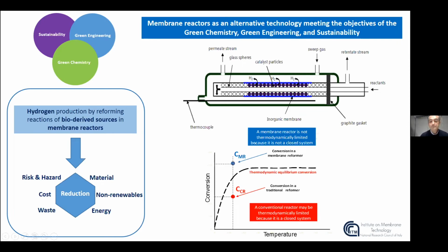And in particular, due to the presence of the membrane inside the membrane reactor module, it's possible to show this theoretical graph, in which, at the same temperature, for a membrane reactor operated at the same conditions of an equivalent conventional reactor, the conversion can overcome the thermodynamic equilibrium conversion of the equivalent traditional reactor. And this is because a membrane reactor is not a closed system, and therefore it is not limited by the thermodynamic equilibrium conversion. Otherwise, by reaching the same conversion of an equivalent conventional reactor, a membrane reactor can be operated at milder conditions, lower temperature, lower reaction pressure. And this allows to reduce the energy inputs required for the process of generating hydrogen.